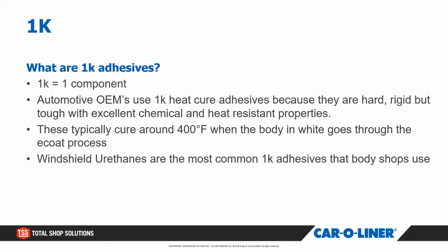And when you look at the different adhesives, that's one of the biggest reasons why collision shops use a 2K adhesive for repairs. One, they can't bake at extremely high temperatures like 400 degrees. And the other thing is cycle time, right? We need to get the job completed and the car back together as quickly as possible. And for 1K adhesives, the most common that collision shops use every day are the windshield urethanes that are moisture cured.